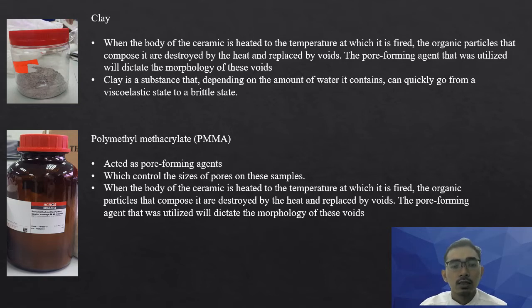Next is the polymethyl methacrylate or PMMA. This material acted as a pore-forming agent. The pore-forming agent function is to control the size of pore that is being created inside the sample. When the body of the ceramic is heated to the temperature at which it is fired, the organic particles that compose it are destroyed by the heat and replaced by voids. The pore-forming agent that was utilized will dictate the morphology of this void.